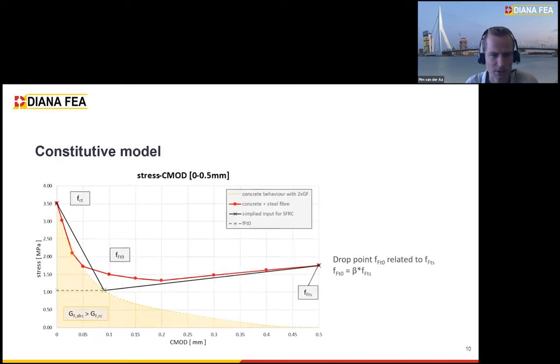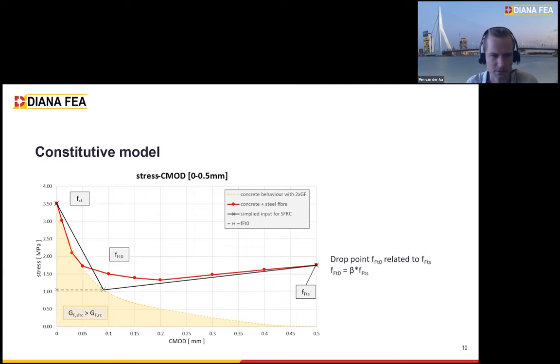If you would simplify it, in this graph we are simplifying basically the red line, which was the concrete plus the steel fiber, with just a simplified input for the steel fiber reinforced concrete. Next to the FFTS point, which was the stress at 0.5 millimeters, we would also like to introduce a sort of drop point, FFT0, the point that you see in the graph, a little bit above 1 megapascal.